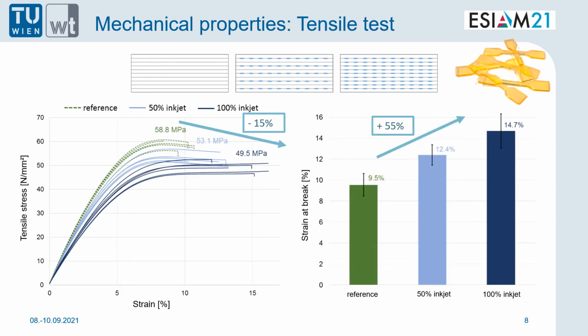To show that those weak interfaces have a significant influence on the mechanical properties of the printed material, we conducted several mechanical tests such as DMA, RSA, impact, and tensile tests. In each we were able to see a softening effect resulting from the ink component, but an increase of impact strength and elongation at break, as shown here in the tensile test results.